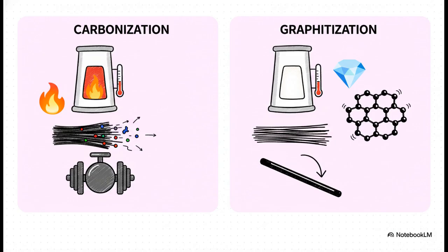But if you want the really top-tier stuff, you have to crank that heat way, way up. That's graphitization. We're talking blistering temperatures, anywhere from 1600 up to 3000 degrees Celsius. It's so hot that the carbon atoms themselves start to line up in this super ordered, perfectly packed crystal structure. And that perfect alignment is what gives you the incredible stiffness of high modulus and ultra high modulus fibers. The hotter you go, the more perfect the alignment and the stiffer the fiber.